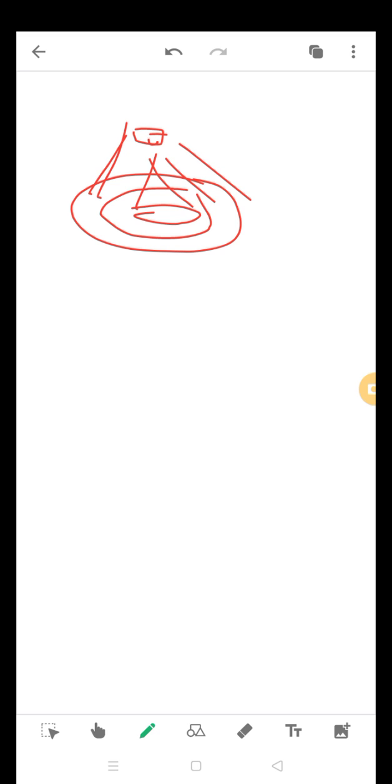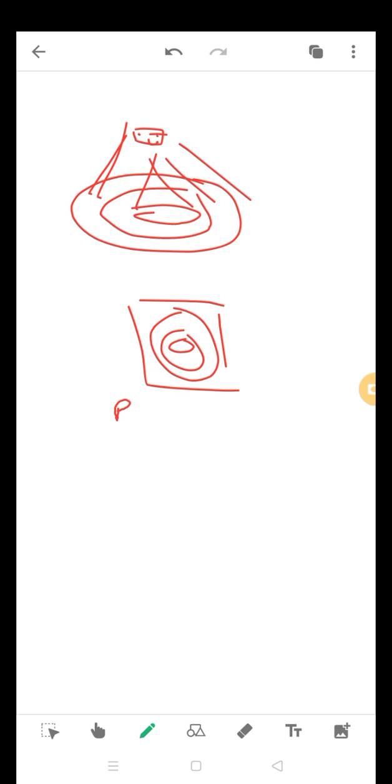If you take the two-dimensional representation of these cones, you get concentric circles. These concentric circles are the bases of the solid cones formed by each of the atomic planes. That's how you get a ring pattern in a polycrystalline sample and a spot pattern in single crystal samples.